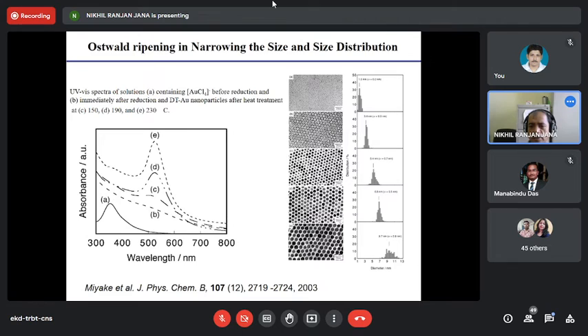You will get different sizes. 1.5 nanometers is converted into 3.4, 5.4, 6.8, to 9.7. So you can increase the size from 1.5 to 10 nanometers, but in each case with a very narrow size distribution, just by heating. By heating, what happens? At high temperature, smaller particles dissolve and grow into larger particles. At a certain size, depending on the temperature, it will stop, and time also dictates what size it will stop.